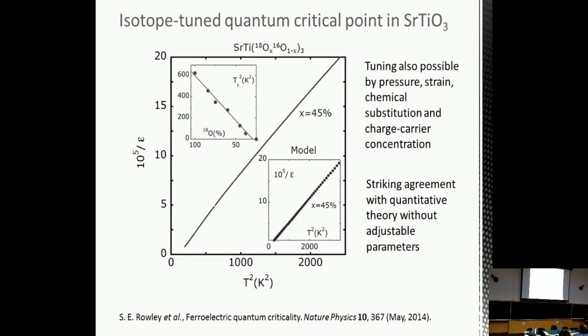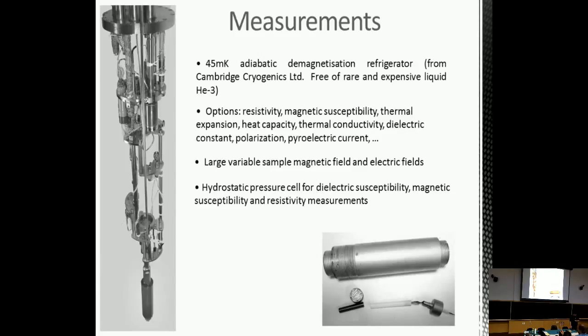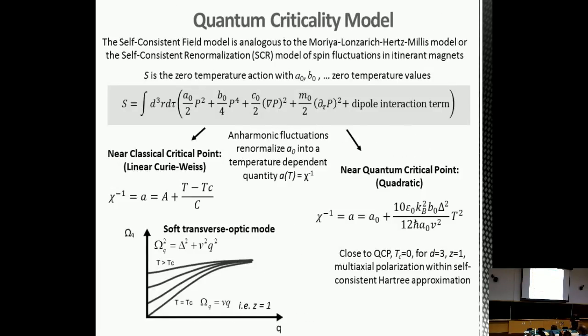So here is the case of the isotope-tuned strontium titanate. And this particular curve is measured very close to the quantum critical point at about 45% oxygen-18 substitution. And you can see here that the measured inverse susceptibility has this remarkable T-squared form. And this is the model calculation result here without any fitting parameters. So there's a very close agreement between theory and experiment without any fitting, coming from a simple quantum criticality model. If you just put in these numbers here, it'll generate this curve in blue.